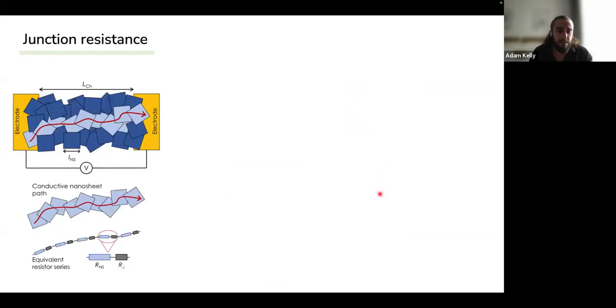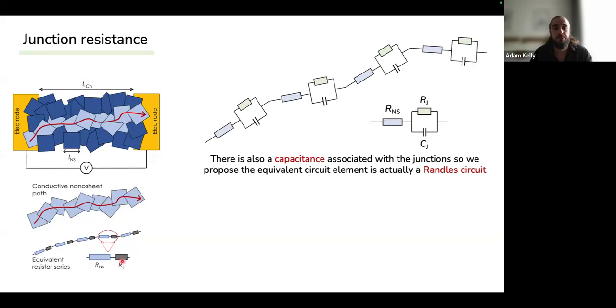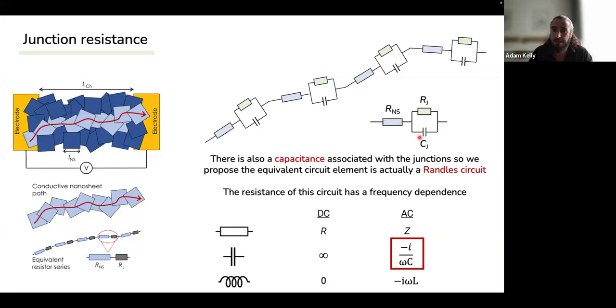So to begin with, we did some modeling. The typical way we do this with particle-based networks is you take a conductive path across the sheets, and you use a resistor chain model where one resistor represents the nanosheet and one represents the junction. However, because we want to measure this, we took note of the fact that there will also be a capacitance associated with these junctions. This means the circuit will be a resistor representing the nanosheet in series with a resistor representing the junction in parallel with a capacitor. Because there's a capacitance in here, this circuit will have a frequency dependence.